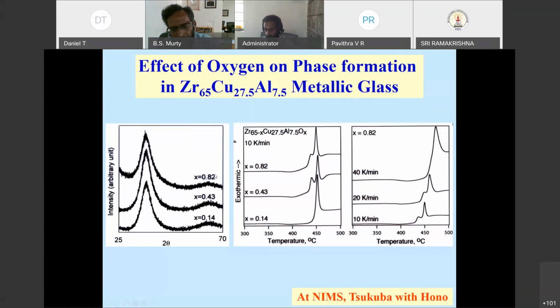I will not go into the details of that. What is interesting is when you increase the oxygen content to a higher level, you start getting 2 DSC peaks, differential scanning calorimeter, if you put the sample. Whereas if you have very low oxygen content, you get only 1 DSC peak.